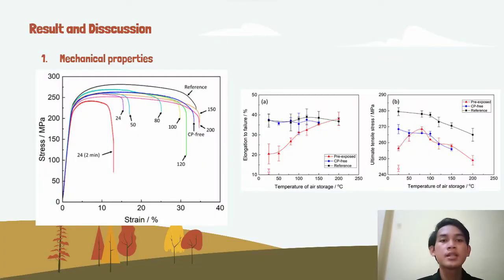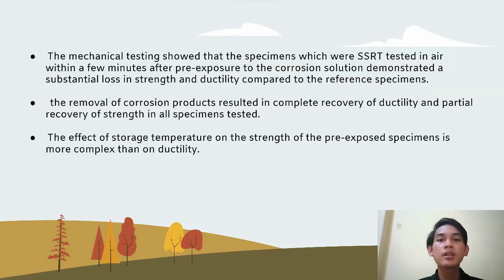And now we will discuss the results and discussion. 1. Mechanical properties. The mechanical testing showed that the specimens which were SSRT tested in air within a few minutes after pre-exposure to the corrosion solution demonstrated a substantial loss in strength and ductility compared to the reference specimens.